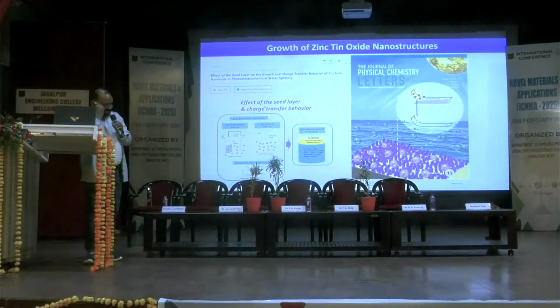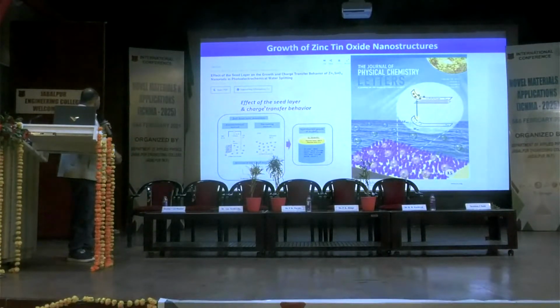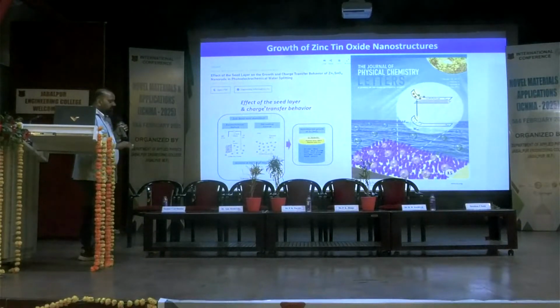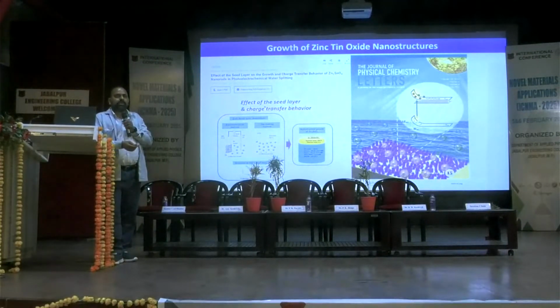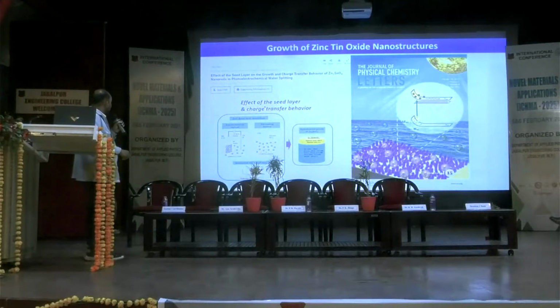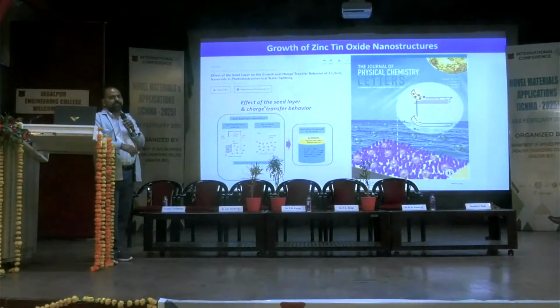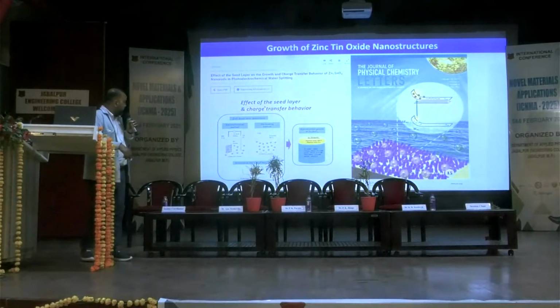And what was the strategy? Basically, we adopted two points. We change the seed layer, because when we start the growth of these structures, they cannot grow directly. So we need to develop some kind of seeding at the bottom. We use FTO as a substrate, and then we grow zinc oxide as a seed layer. We adopted two approaches. One is that we prepared a solution of zinc oxide and dip coated the layer, and the other is electrochemical deposition of the zinc oxide. In this whole study, we kept our focus on investigating the effect of the two different seeding approaches on the structural performance as well as the photoelectrochemical performance.